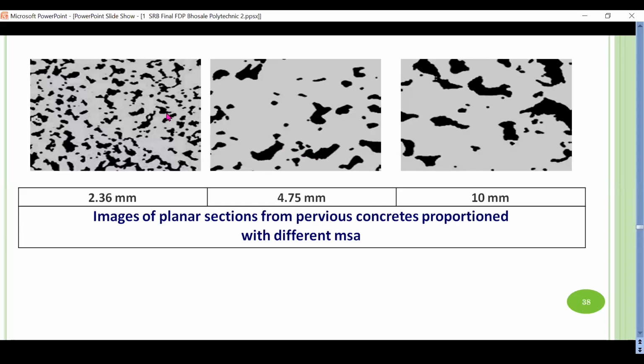If you see, for 2.36 the pore size is different. For 4.75, it is larger than what we have for 2.36 mm. And for 10 mm coarse aggregate, the pore size is still larger than 4.75. However, the total voids present in each sample are around 20 to 25%, and the percolation rate for all the three specimens is equal.